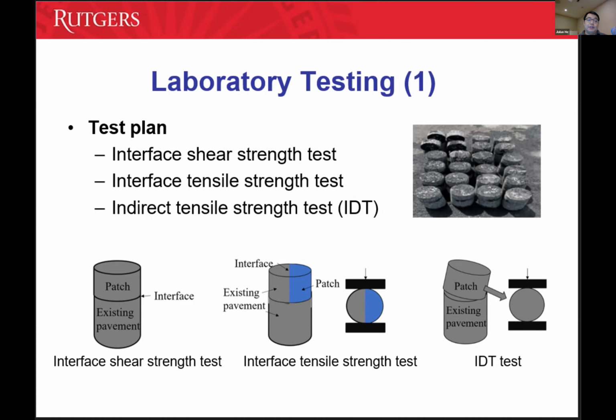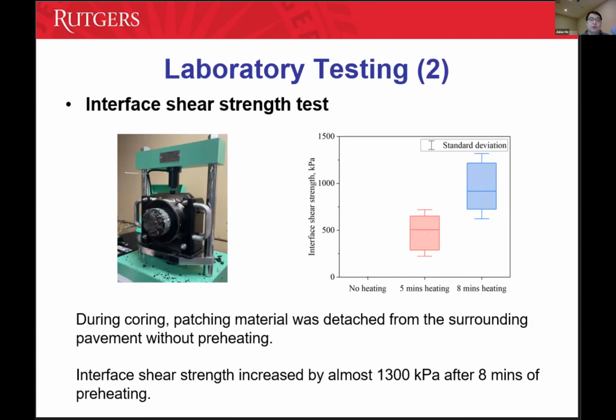So the first two tests are more like indicating the interface bonding. The third one is more for the patch material strength itself. So this will be related more to the bonding between the patch and the depression, or the possible raveling of the patch itself. For the shear strength testing, you can just use a modified Marshall tester. We didn't do confinement in this case because we really want a quick comparison, and also the testing can be adopted by the DOT and the real field laboratory without complicated equipment to apply the confining pressure to the bonding condition.